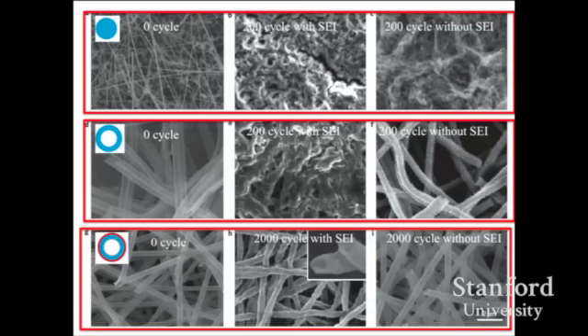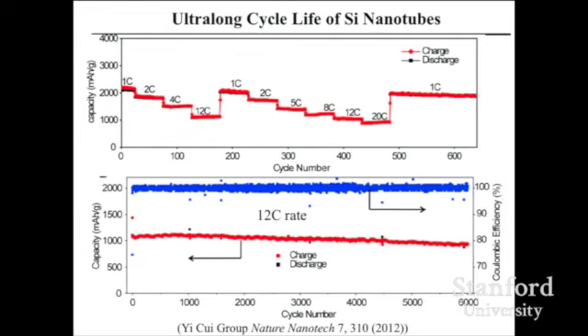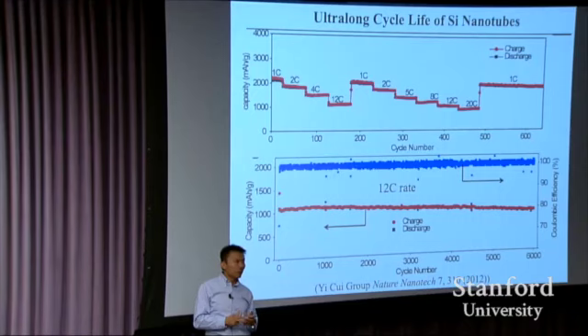So using this type of structure, comparing silicon wires, single wall hollow tube and a double wall hollow tube. After 2,000 cycles, you look at the surface, it's beautiful, it's clean. It doesn't decompose much electrolyte, but the other two cases decompose too much. So this confirms the double wall tube is stable. This allows us to run 6,000 cycles in the half cell, at least proving the material is now stable. After this study in 2012, I do feel like we finally understood the material design principle to make these types of materials work for the next generation.